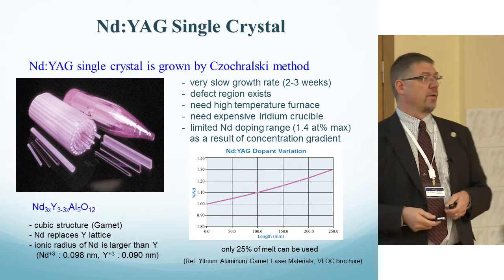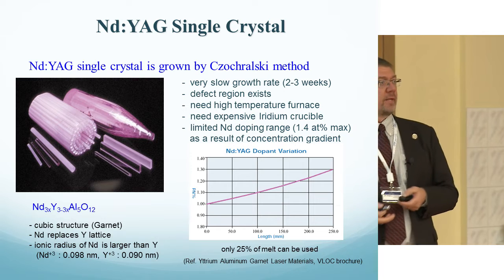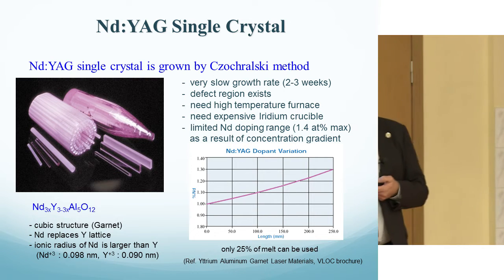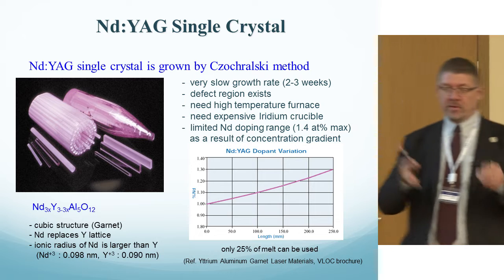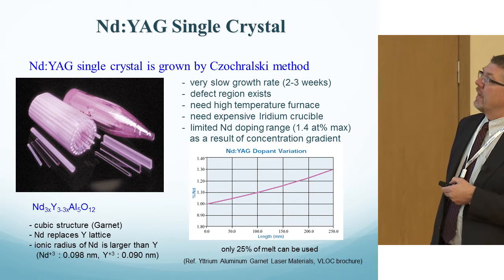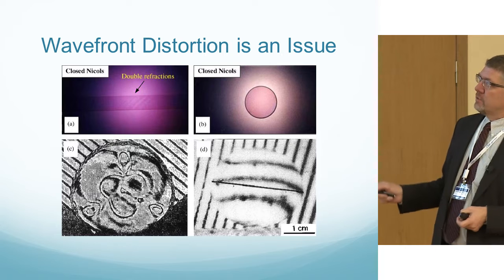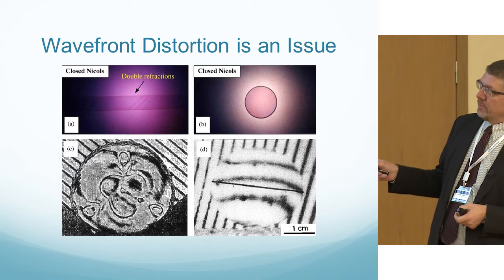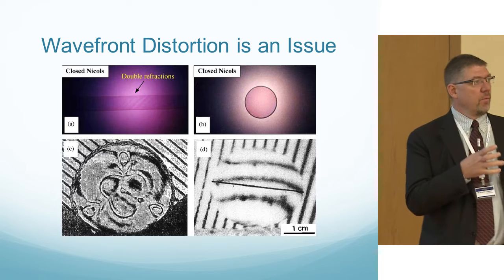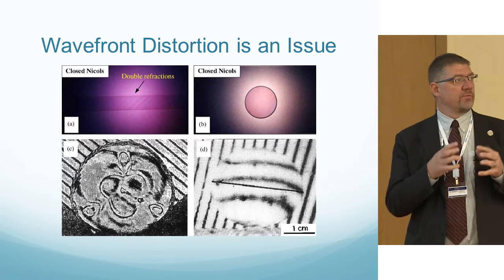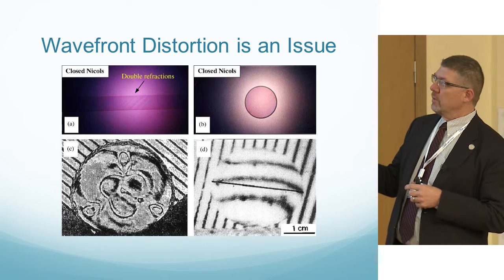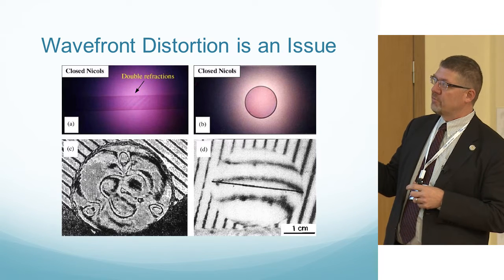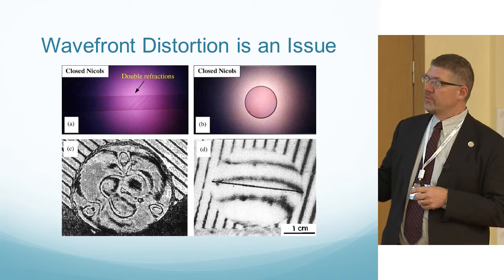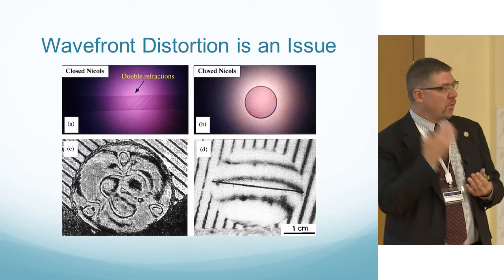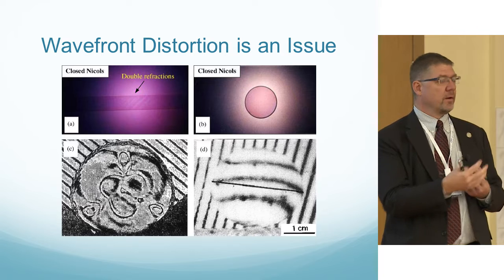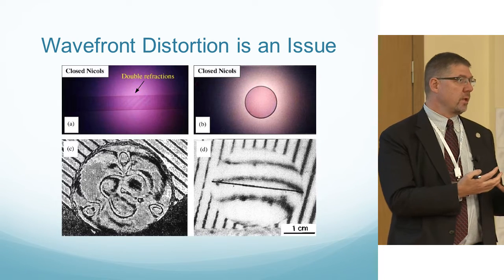My previous company, we had 25 growth furnaces, so we had about 28 of those buckets. So it's a huge investment from a corporate standpoint to try to buy the material just to grow the YAG in. A couple of the challenges are, if you look down the length of the material in an interferometer, when these are growing, they're growing with an interface. They're also growing with high stress regions. You can see here at every 120 degrees, there's a high stress point in the interferometry. All of this is useless material, because as you propagate the wavefront of a beam through there, you're going to distort it, and it's not going to come out with a clean mode.